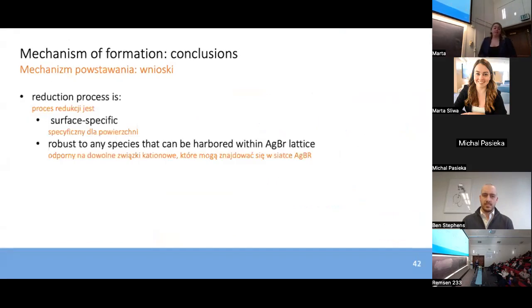So having spent all of this time trying to understand how these particles form and discovering that the process is surface specific, that process being the formation of the dimers, and also we think robust to any species that we can effectively harbor within that silver bromide lattice. If that species can also make its way to the surface where the L-arginine is, it can hypothetically undergo concurrent reduction with the silver cations and form some sort of other material.